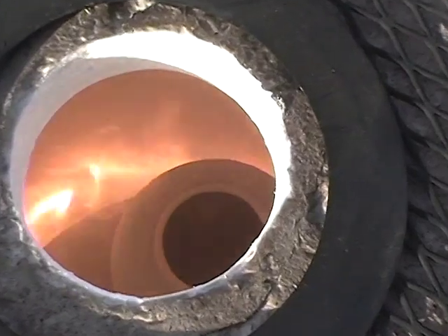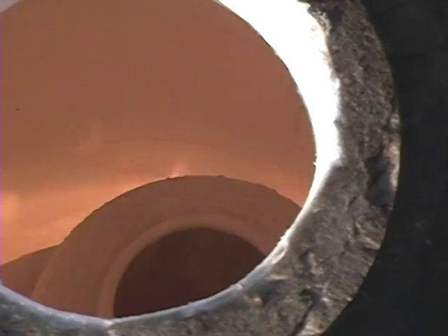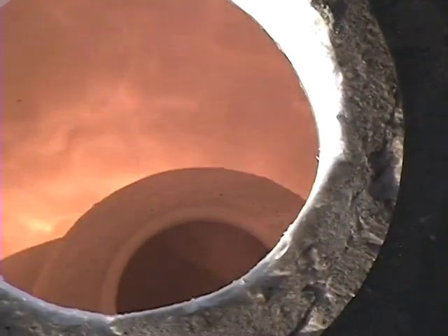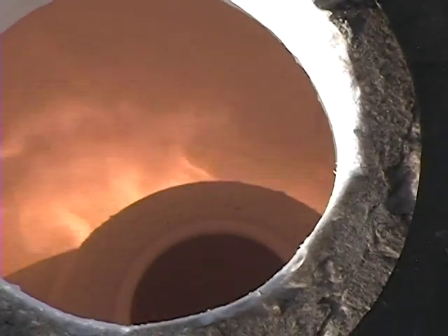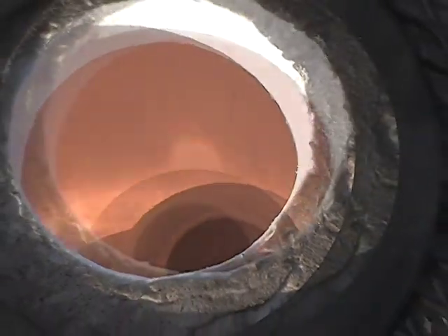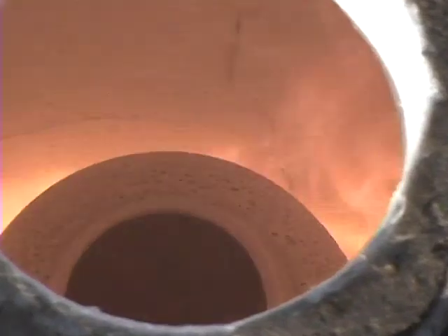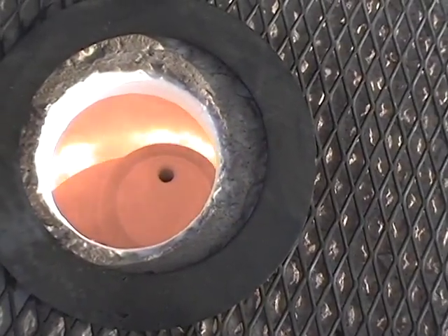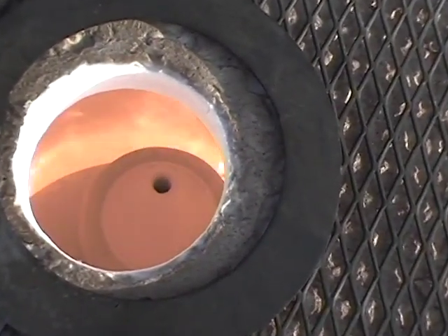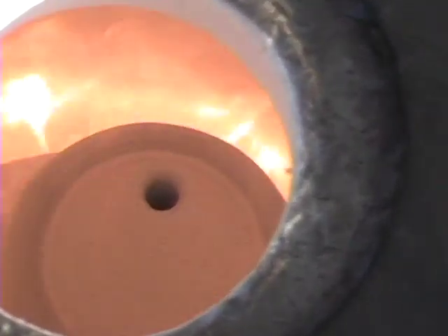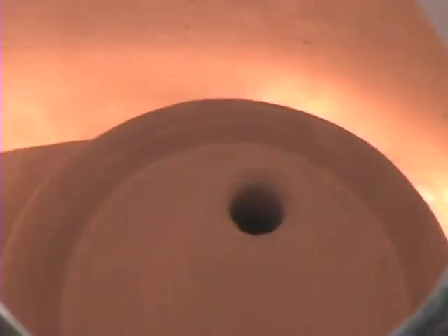After about 10 or 15 minutes, some of the glazes you've used will actually appear to be foamy on the surface of the pottery. This is a good indicator that the glazes are actually beginning to mature, and it's completely natural. Some glazes will not perform this way, so it's always good to try to find out which ones do and which ones don't. Here's our homemade example, and as you can see, this particular type of glaze doesn't like to foam up as much as the other ones.